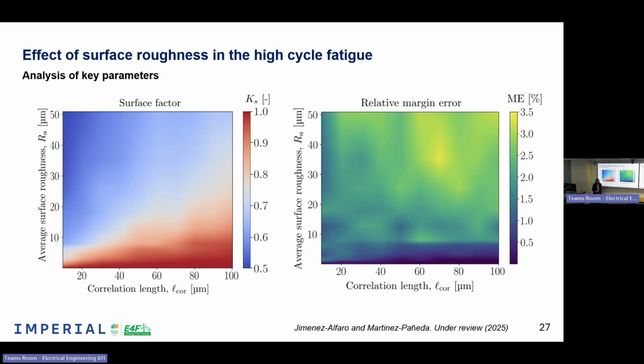That is really critical. Imagine a polished specimen with a certain load has 1 million cycles. It's broken at 1 million cycles. But if we include this surface roughness, it will be broken with the half. It means with 500,000 cycles, just the half. Is very critical. And since we are with a random distribution, I have also represented an operational map for the margin error, the relative margin error.